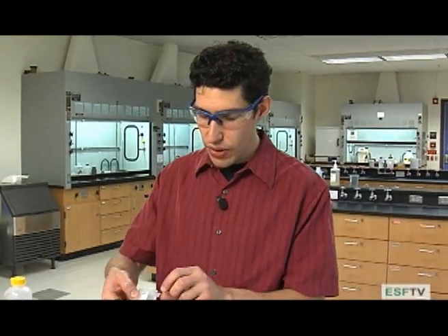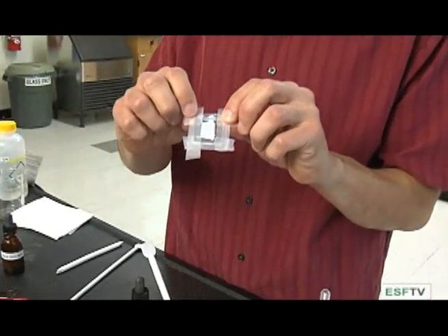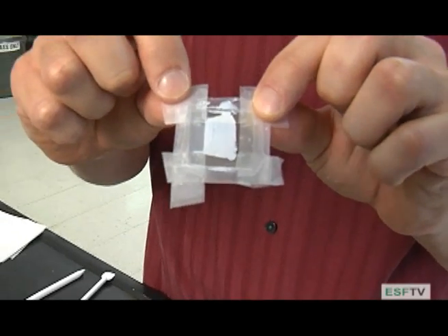That looks pretty good. If for some reason you have some streaks or it looks not quite as smooth, you can use the stirring rod and pull back again until you get a nice smooth paste. Once that paste is dried, and it will take about five or ten minutes, you'll have something that looks like this. It is dry, but it still has the tape border on it.